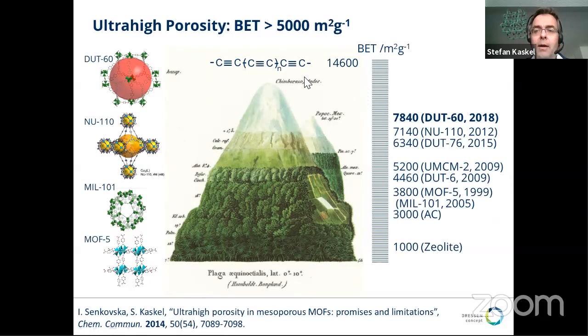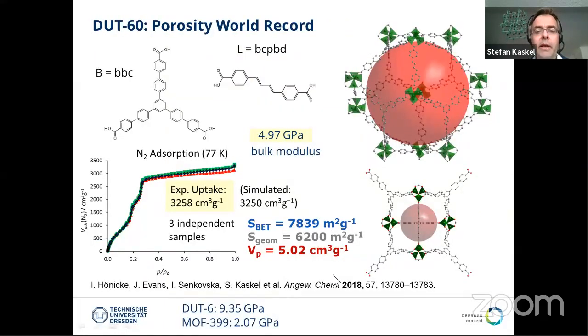Now, Omar Farha, in his JACS paper, pointed out that there may be a theoretical limit. Of course, this is imagination. When we imagine a polyacetylene strut, which becomes longer and longer, infinite length, then we might achieve a specific surface area or a geometric surface area of almost 15,000 square meters per gram, which has not been achieved so far, of course. And I think one of the reasons, and this is what we basically pointed out in our publication in 2018, reporting this ultra-high porosity in this type of material here, 7,800 square meters per gram.